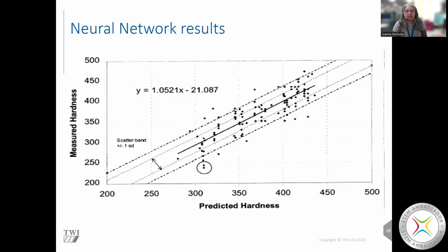Yes, it would, because the higher the chromium, the more the way that the heat interacts with the material changes. So we do need to put those caveats around the neural network. So we can't just use it for every steel that exists. We have to say, well, it's okay up to 3% chromium because it's been tested on up to 2%, and we're happy that we could go up to 3% without falling outside of that.